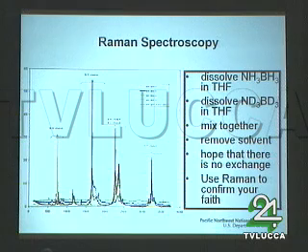So we talked to our Raman spectroscopist, and she was able to look at the solids of all these materials. Since nitrogen and boron are relatively light elements to begin with, if you put deuterium on there, you can significantly shift the BD stretch. So you can look at the Raman spectra and get a fingerprint of each of these species. The idea is to focus on this BN stretch area, and you can see both the B10 and B11 isomer, as you'd expect.